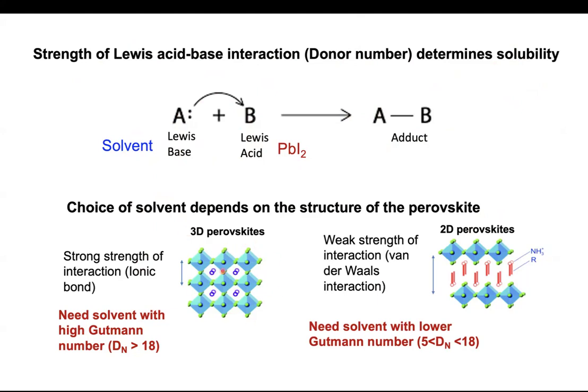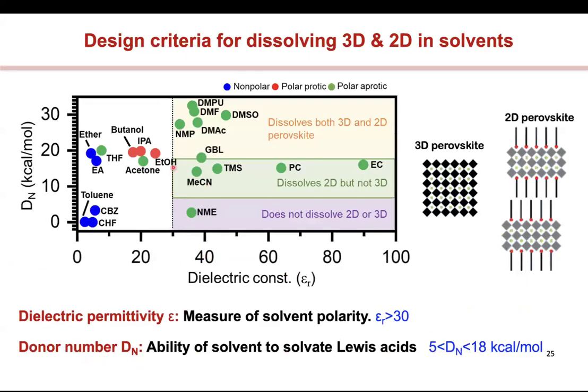Now look at these 3D perovskites. They are basically a three-dimensional network, and they have a strong ionic bond, right? They are essentially a complete network of ionic bonding here. And so you need a solvent which has a high Gutmann number, right? A donor number which is greater than 18 in order to break this bond, right? And that's what we saw. In fact, you need a donor number which is greater than 18 here in order to dissolve a 3D perovskite.